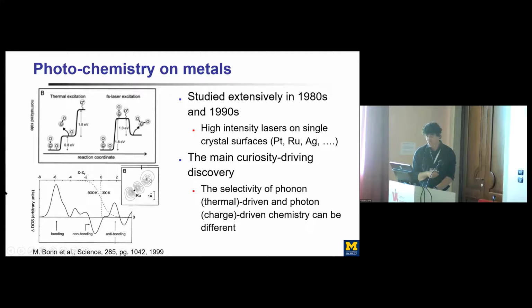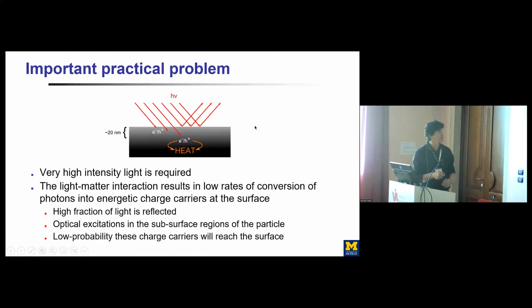So this was a very interesting discovery. However, the problem is that there's a really important practical limitation here. The practical limitation is that you have to have a very high intensity laser to be able to induce the formation of these energetic electrons at the surface of these nanoparticles, or the surface of the metal single crystal in these particular experiments. And the main reason why you need this high intensity light is that you reflect a large